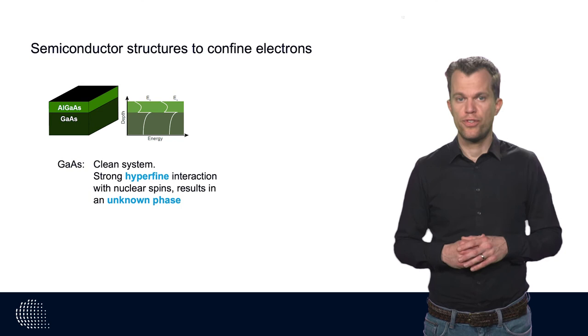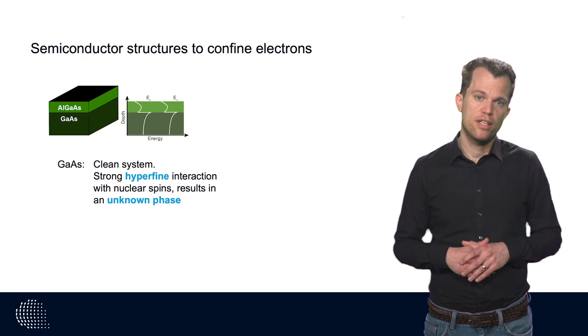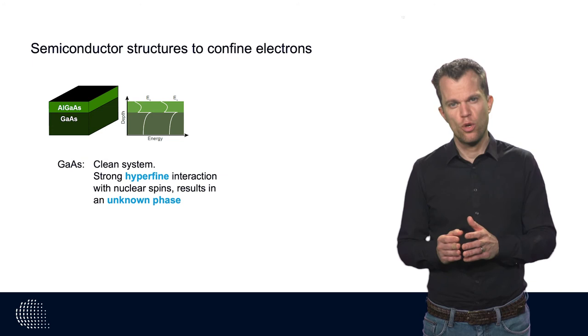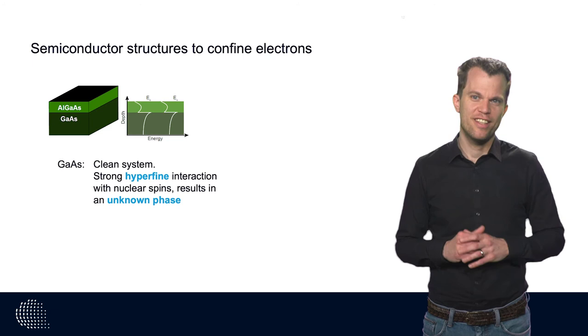Unfortunately, gallium arsenide is also a material with a large abundance of nuclear spins. These nuclear spins fluctuate over time and can interact with an electron residing in a gallium arsenide quantum dot. This interaction is called a hyperfine interaction and it affects the resonance frequency. Thus, the nuclear spin fluctuations will quickly result in an unknown phase. Indeed, there are many factors relevant in determining the phase stability, but fortunately there are also ways to resolve this.